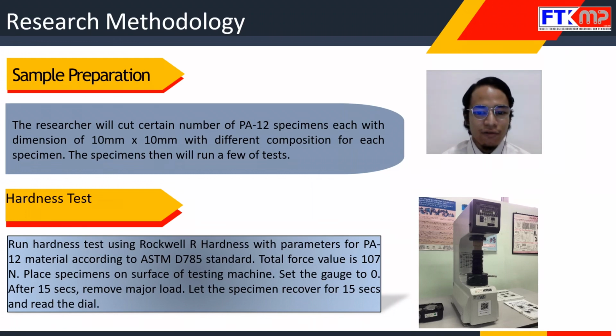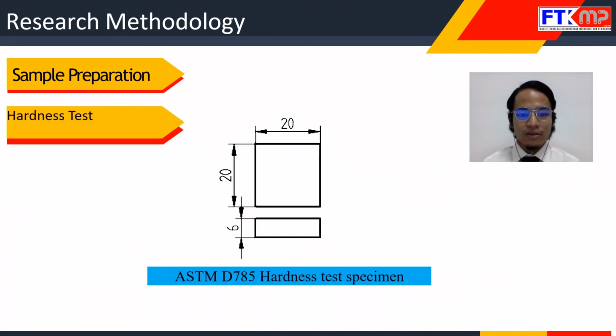The total force, as you can see here, is 107 Newton, and then we place the specimen on the testing machine surface and set the gauge to 0. After 15 seconds, I will remove the major load, let the specimen recover for 15 seconds, and read the dial. This is the specimen for the hardness test, with dimensions according to the ASTM standard. This is the dimension from the drawing I made. The thickness is around 6 mm, the length is 20 mm, and the width is 20 mm too.